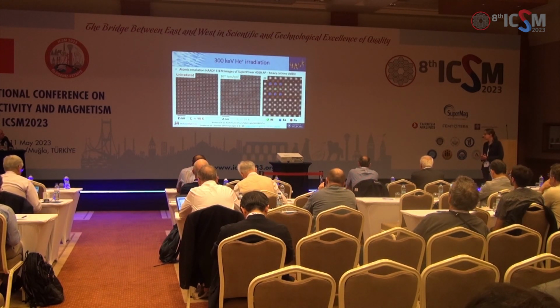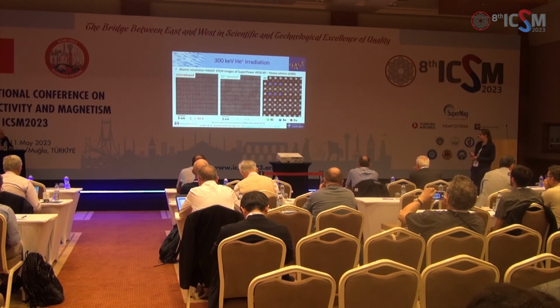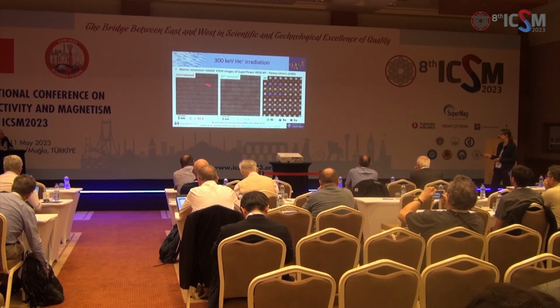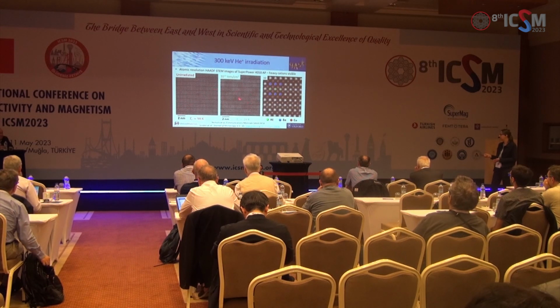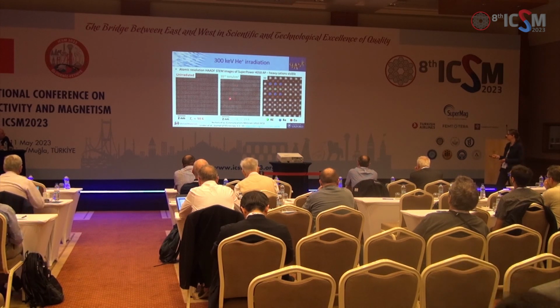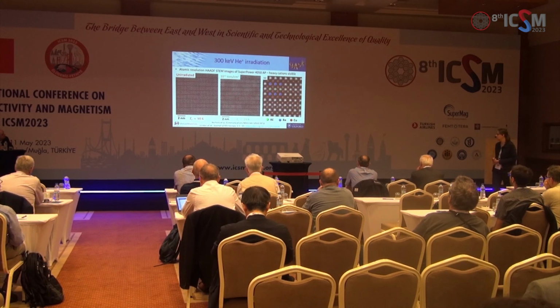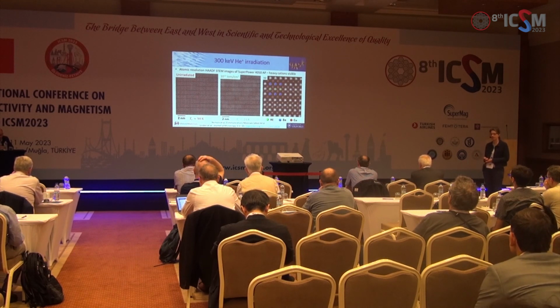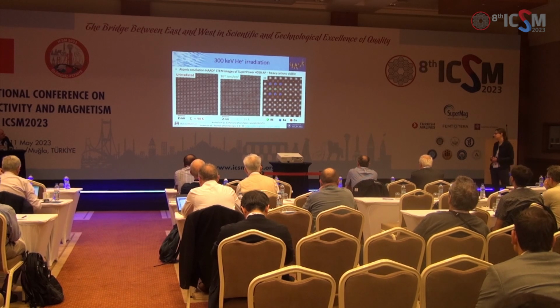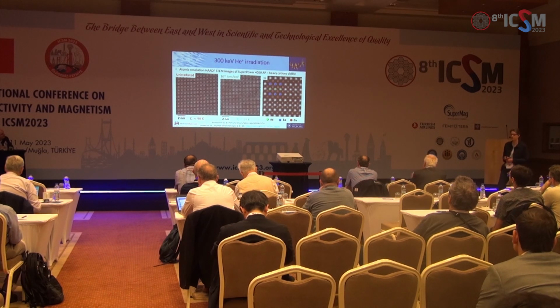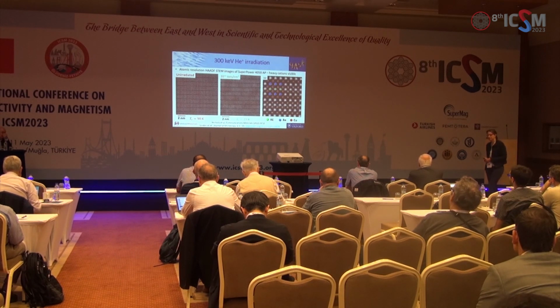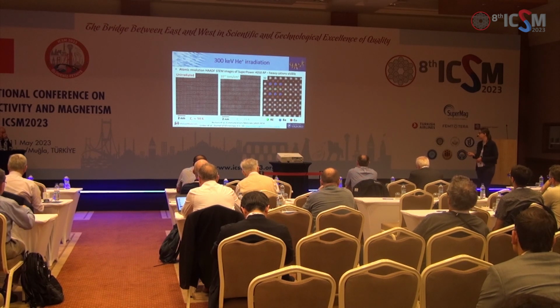So here's some electron microscopy. The left is a sample that's unirradiated, a coated conductor that's unirradiated. Here is the irradiated version. This has been irradiated so much with helium ions that it now no longer superconducts. However, I think you probably noticed that every sort of atom column you see in the pristine structure is also there in the irradiated structure, so it's not completely damaged the material. You can look here if you want to see which atom is which. You see all of the cations in this kind of imaging mode. We don't see the oxygen ions because they're too light. So we can be pretty sure that the cation lattice isn't really completely damaged by this irradiation, even though superconductivity is all gone.